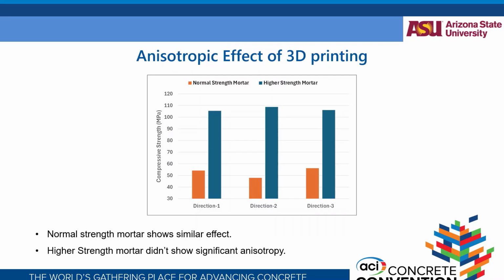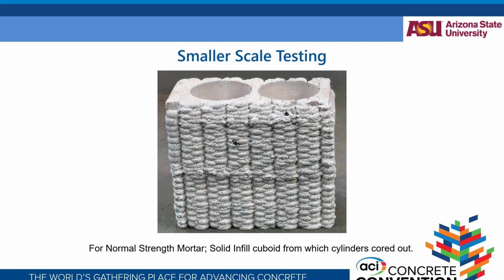So why does direction 2 have that lower strength? We wanted to see it based on some mixes we did before. You see that there will be this alignment of interfilament joints. This was a large solid section that we printed, and we cored out 2 cylinders out of it to reduce the actual equivalent area. Now that will have some detrimental effects to it, most probably.